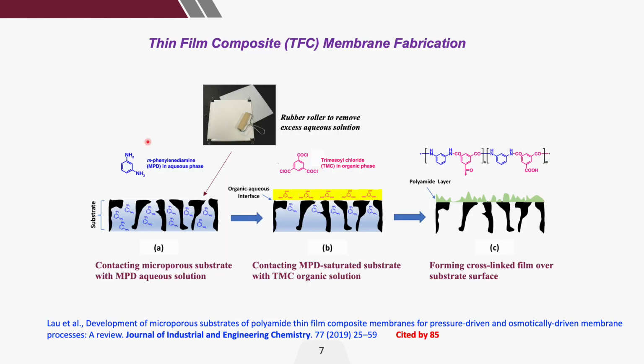So this diagram shows you how to prepare the polyamide thin film composite membrane using interfacial polymerization technique. First, you need to have a microporous substrate, and this substrate typically is actually an ultrafiltration membrane. Then you pour in the first aqueous solution containing a first monomer. After that, you contact this same membrane with the second monomer. Once these two immiscible monomers mix with each other, they start to cross-link to form a polyamide layer. And this layer actually is very thin, just several hundred nanometers.